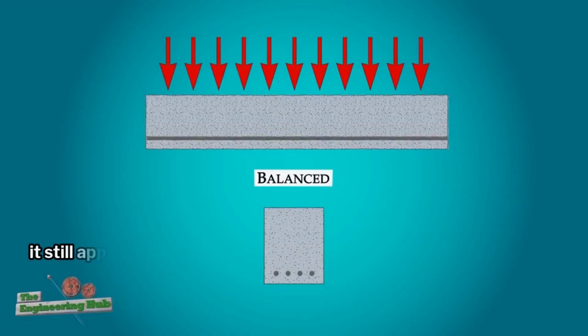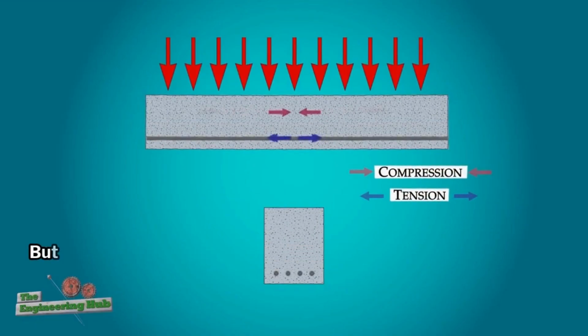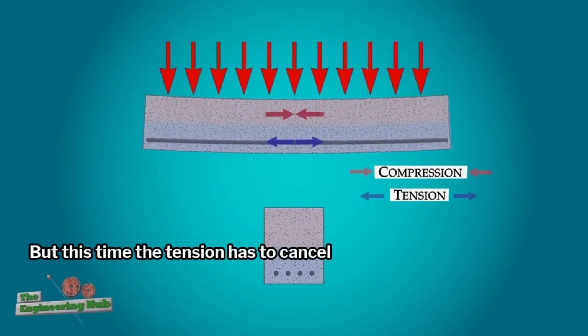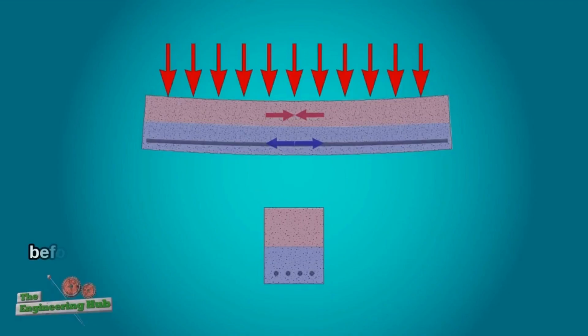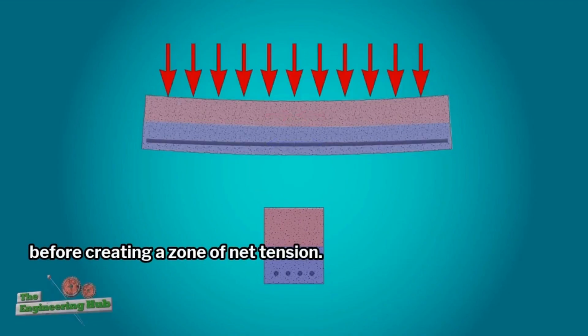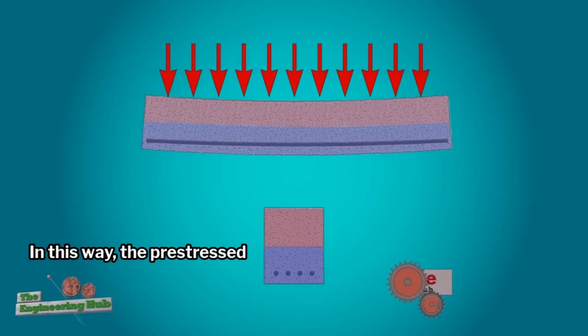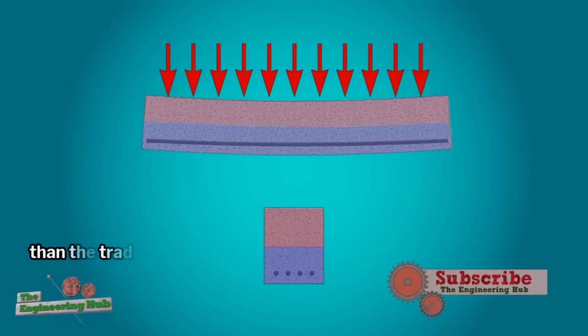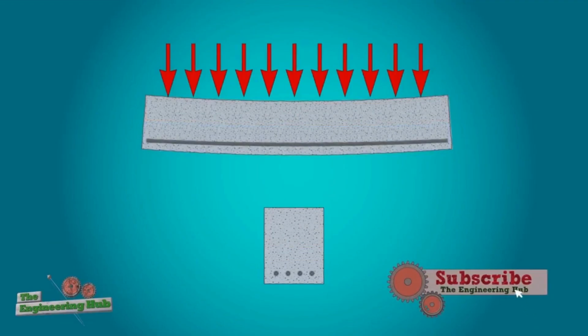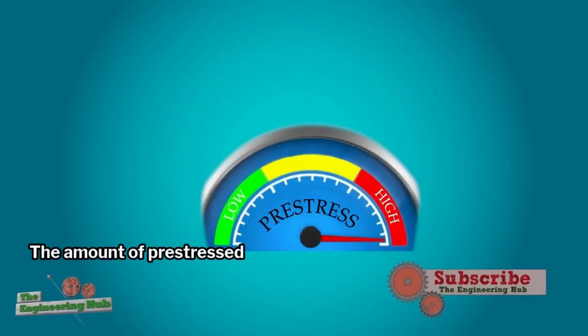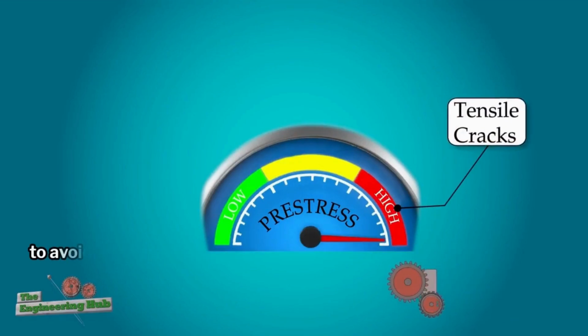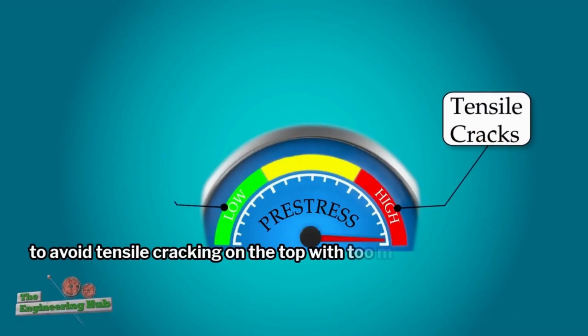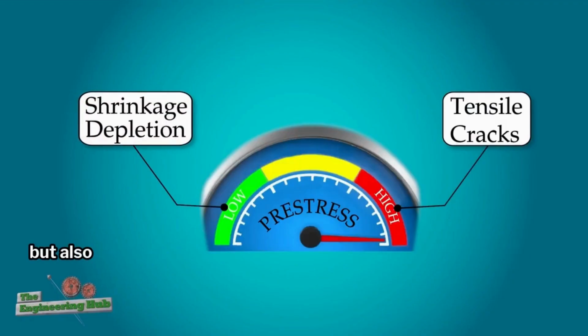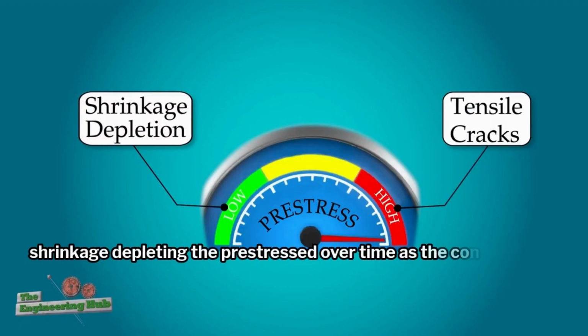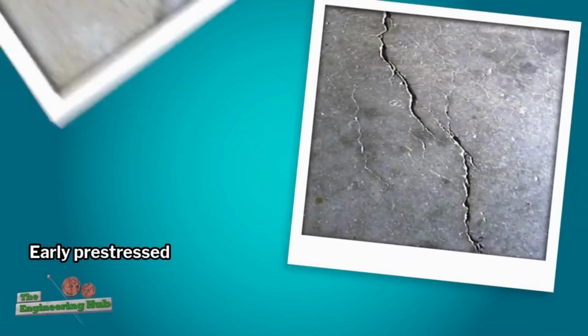Once the beam begins taking load, it still applies tension on the bottom half, but this time, the tension has to cancel out some pre-stressed compression before creating a zone of net tension. In this way, the pre-stressed beam is able to take more load than the traditionally reinforced concrete one, all else equal. The amount of pre-stressing has to be carefully calibrated to avoid tensile cracking on the top with too much pre-stressing, but also must be enough to avoid concrete shrinkage depleting the pre-stress over time as the concrete cures.